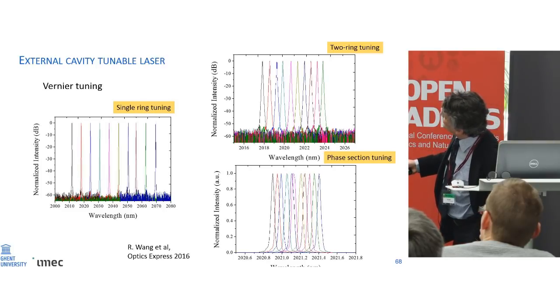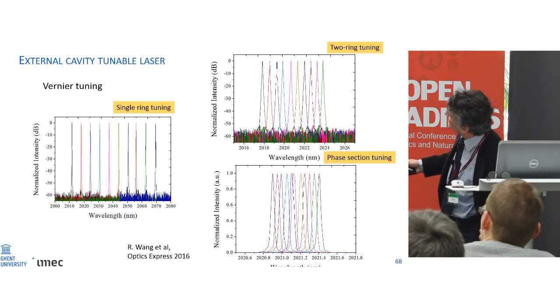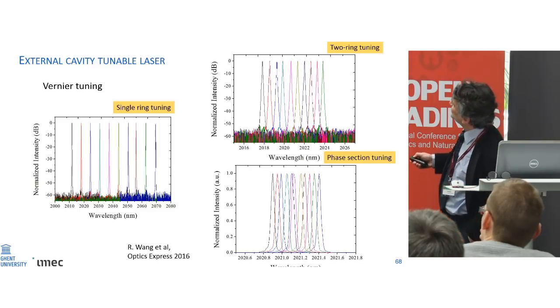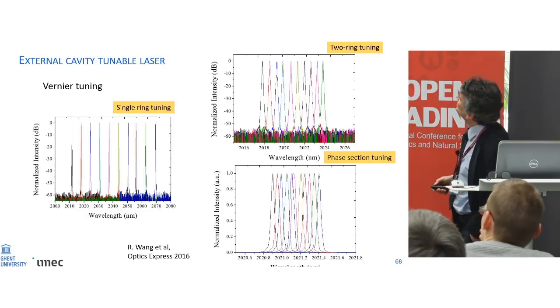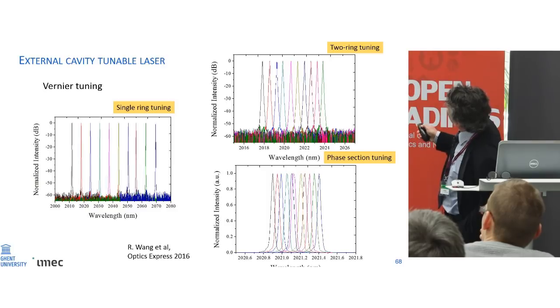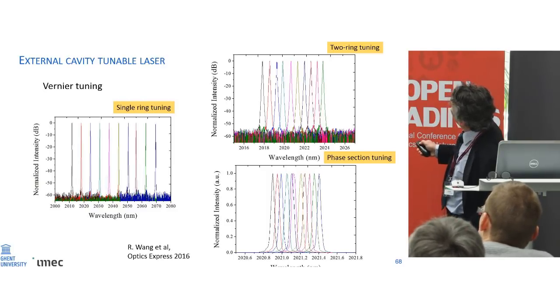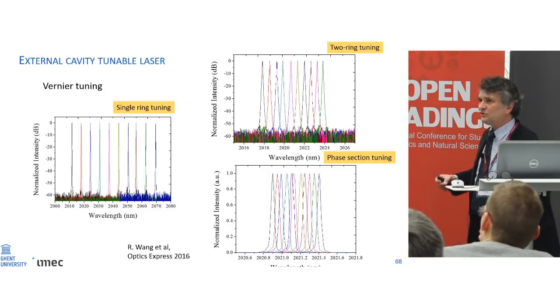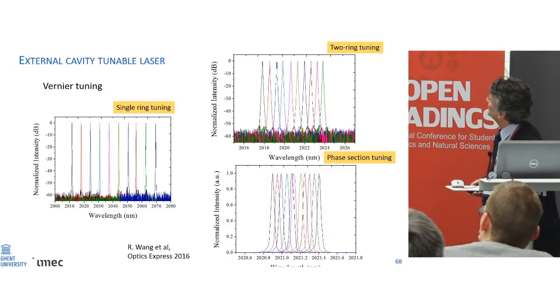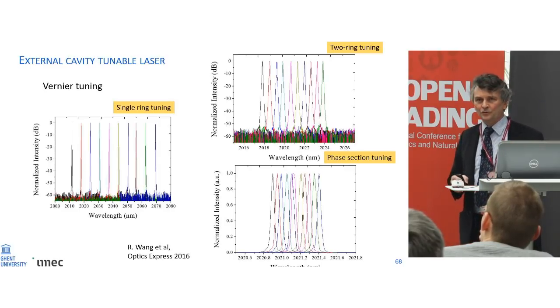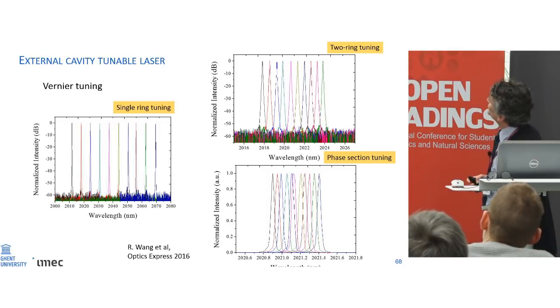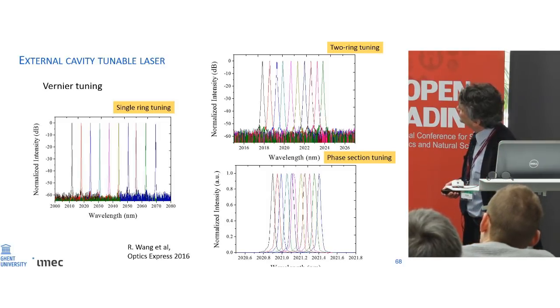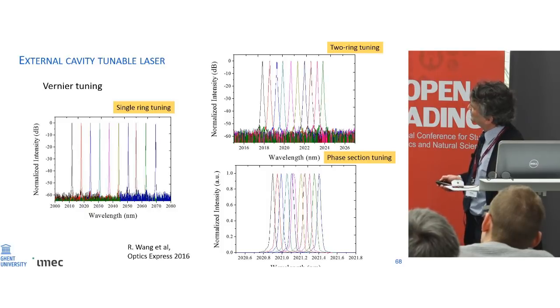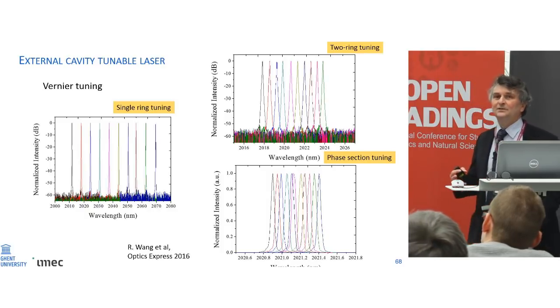The left curve you see is discrete tuning. You see the laser tunes from 2010 nanometer to 2070 nanometer. So that's a relatively broad tuning range. But it's not continuous. It jumps from one peak to the other upon driving up the current to the microheaters. Here, this is already finer tuning, you see from 2018 to 2024. And then with the phase section tuning, we can do extremely fine tuning of the device. So by playing with the three currents that can come out of an electronic control circuit, we have continuous, single mode tuning all the way from 2010 to 2070. So you can imagine lots of applications for this.